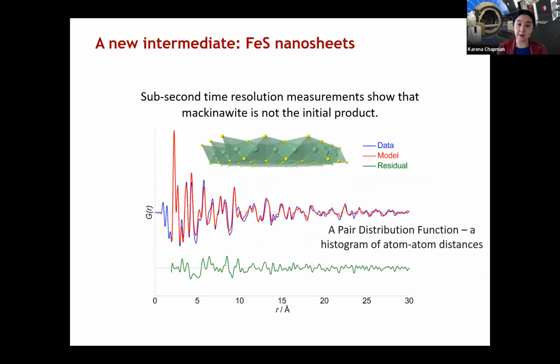After testing various structural models, Michelle was able to figure out that early in this reaction, what's forming is just single isolated nanosheets of this iron sulfur product, which then ultimately stack together to form that mackinawite structure. So this would be the amorphous or nanoscale intermediate that people had previously identified.